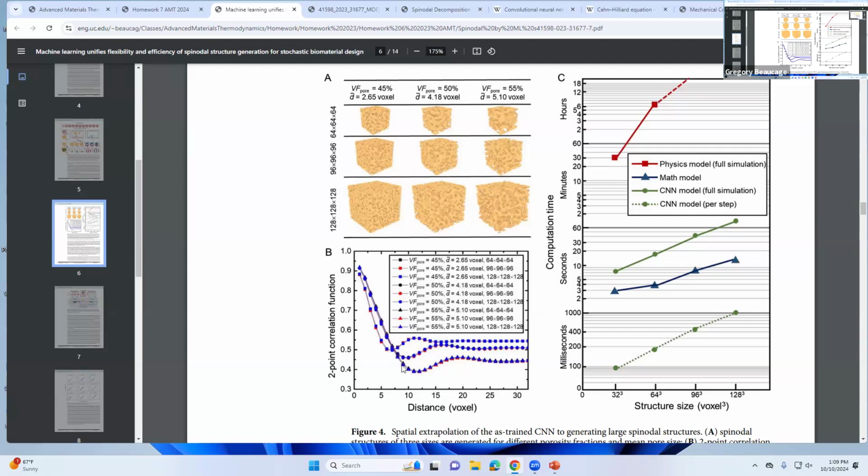And the other thing you can get is that you go to smaller and smaller distance of this thing. And then you're measuring as if it's a flat surface. The correlation function has to do with the surface area. In other words, the amount of surface area versus the volume. So say you have two things separated by that, and they're in the solids. That's yes, till you get to the surface, and it's no, right? And then you get into the void, and it's no. So basically, the only no part is at the surface. So that's going to give you the surface area for the correlation function divided by the volume, because you normalize them by the total. So anyway, the slope of this thing is the negative of the surface to volume ratio.